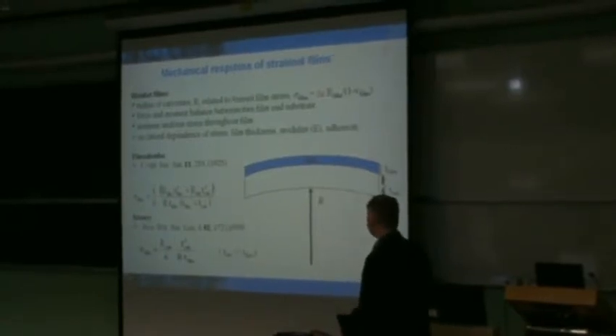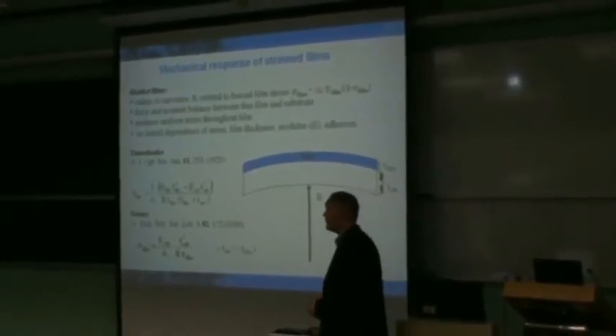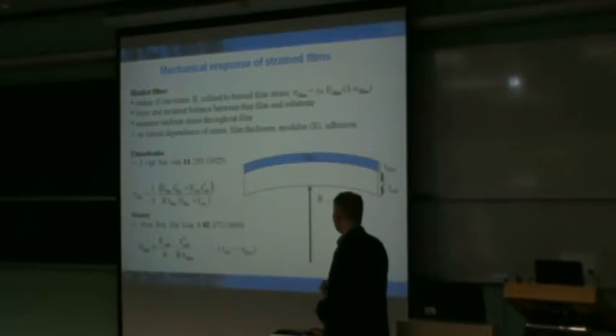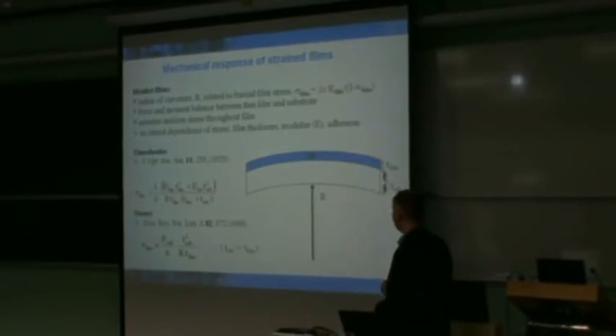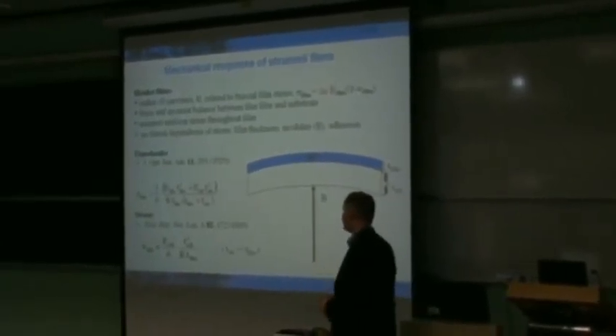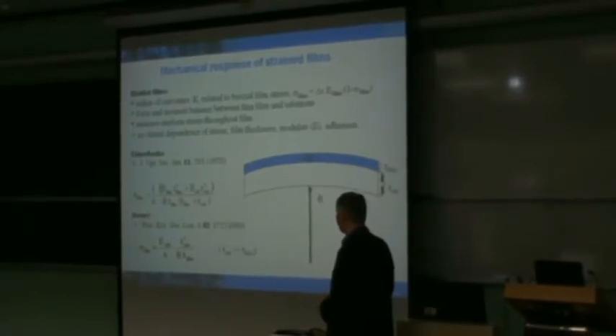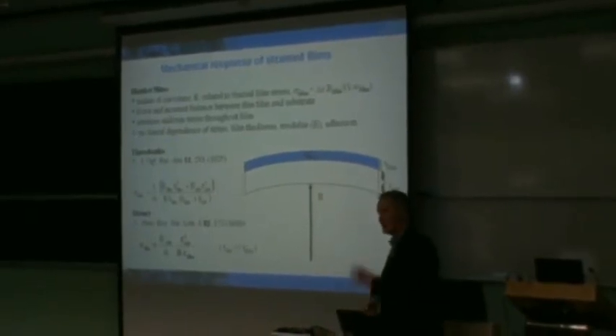So most people might be familiar with the fact that the mechanical response within films can be easily seen and was observed, again, about the same time frame, over 100 years ago. If you have, say, a wafer, and you deposit a certain film with a residual stress on it, the way to equilibrate that stress involves bowing that wafer. And in some cases, this can be alarmingly high in terms of the curvature that exists within the wafers.